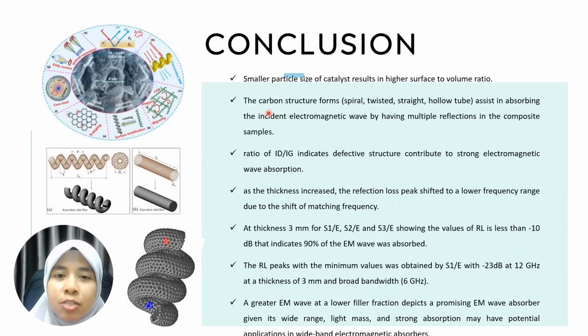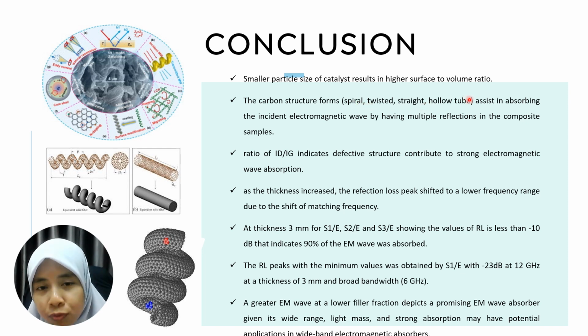Finally, for conclusion, smaller particle size of catalyst results in higher surface to volume ratio. The carbon structure forms, which are spiral, twisted, straight like hollow tube, assist in absorbing the incident electromagnetic wave by having multiple reflection in the composite samples. The ratio of ID over IG indicates defective structure, contributing to stronger electromagnetic wave absorption. As the thickness increases, the reflection loss peak shifts to a lower frequency range due to the shift of matching frequency. And at thickness 3 mm for S1E, S2E, and S3E, the value of RL is less than negative 10 dB, which indicates 90% of the EM wave was absorbed.